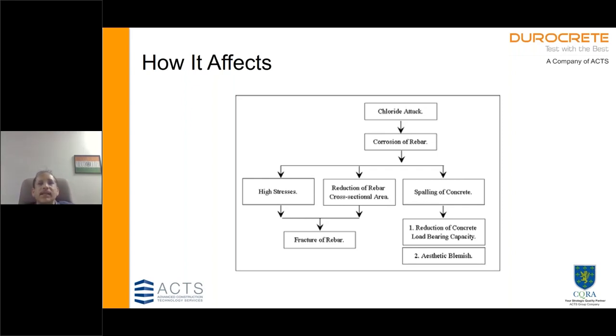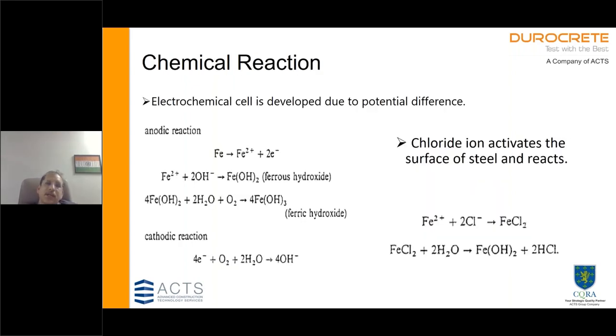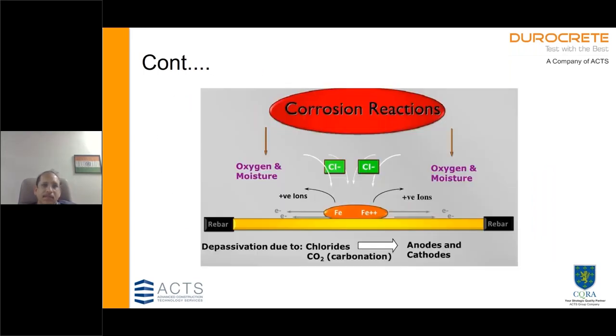So in this diagram, you can see that the corrosion of bar, there are high stresses, there is a fracture of rebar, spalling of concrete, and corrosion is the most common reaction that affects the concrete, RCC buildings. So there is an electrochemical cell that is formed inside, and this is accentuated by carbonation, because carbonation reduces the pH of concrete. Normally the pH of concrete is more than 12, but because of carbonation, it can come down to almost neutral, maybe 8 or 9, and that is when the passivity film that is formed outside the rebars is lost, and you have starting of the corrosive reactions.